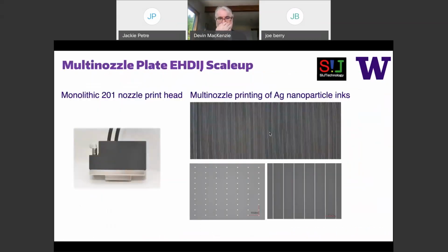And this is an example of that. This is the print from SIJ that we've been developing. Actually, it's a lot of lines, and these are probably about 7 to 10 microns in particular, continuously printed in one pass to produce this sort of resolution.